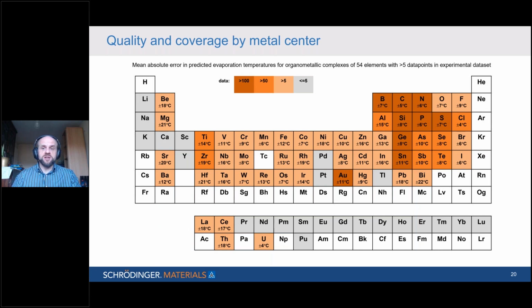And the non-metals, we had a lot more data, a lot easier to find. And so the error is correspondingly lower. Some of the transition metals, the error is a bit higher because we had less data, but you can see very good extrapolation. So even where there are 5, 10, 15 data points, the fact that it's part of a larger model gives a really, really low error, as low as 10, 15, at worst 20 degrees Celsius. So more than enough to make a prediction about whether something is volatile or not.